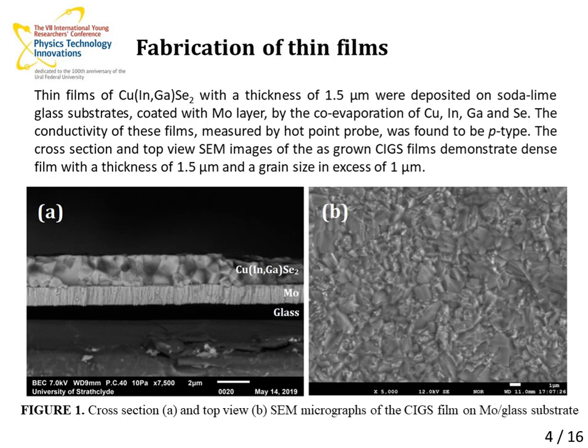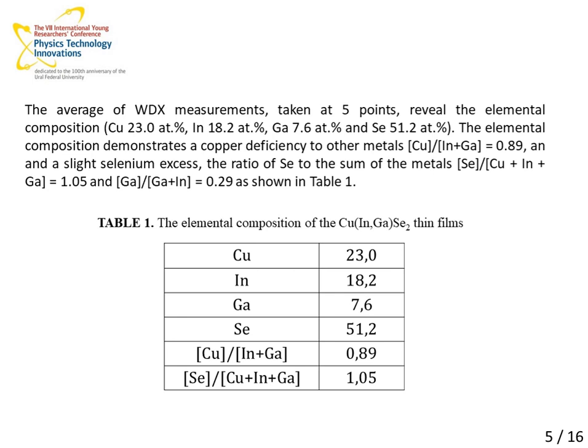Thin films were deposited on soda-lime glass substrates coated with a molybdenum layer by the co-evaporation technique. Here you can see a cross-section and top view of these films. The elemental composition demonstrates copper deficiency relative to other metals and a slight selenium excess.